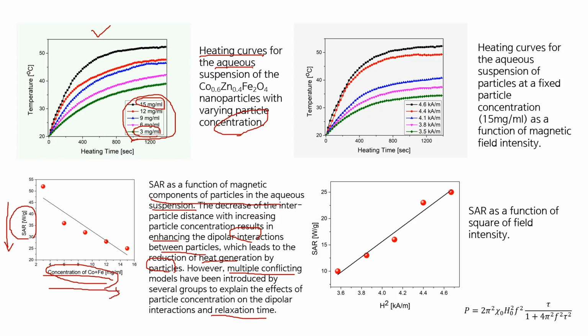Next, we fixed the concentration of nanoparticles, and then we changed the amplitude of the magnetic field. So this figure shows the data. So these are heating curves for the aqueous suspension of particles at a fixed particle concentration of 15 milligram per milliliter, and we changed the magnetic field intensity. So as the magnetic field intensity increases, more heat is generated. So that is expected by this relationship.